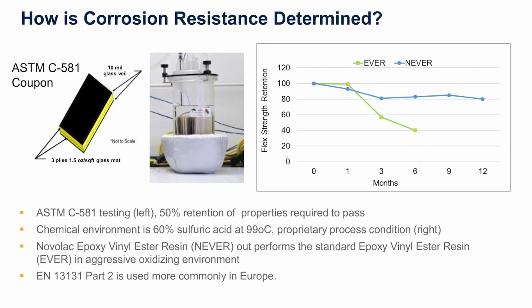So how do we know how this stuff is going to perform? We actually do empirical studies. We do corrosion resistance evaluations. So I don't know if you can see this quite well, but this is a reactor in our lab, and these are ASTM C581 corrosion coupons. And there's a method for making these coupons. It's a standard that's been out there for a long time.